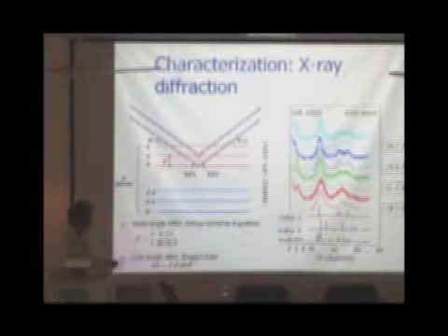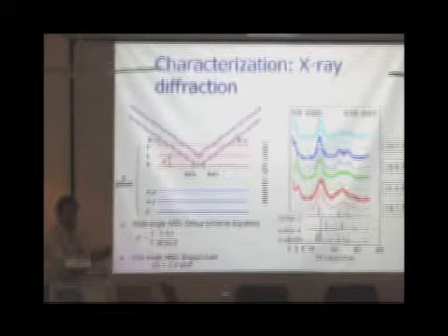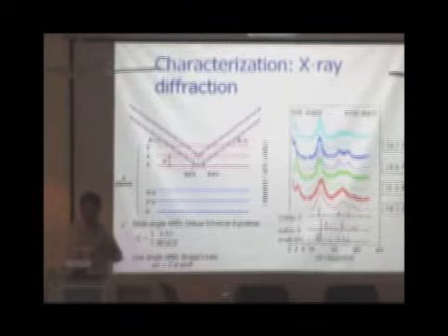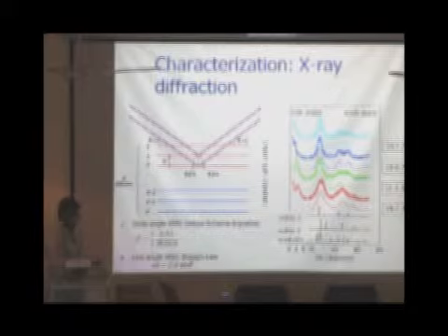The other thing is you can also try to align these particles and form superstructures, and if you form superstructures, then the X-rays will diffract between these particles and you can get low angle peaks, which according to the Bragg equation would correspond to the ordering of these particles.